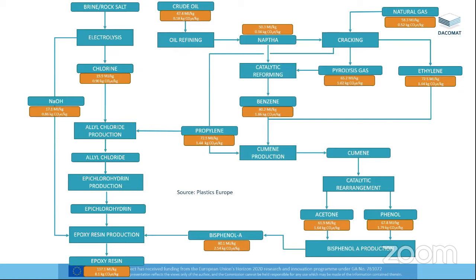What we're basically doing is extracting ingredients, feedstocks from nature, and then we process those feedstocks. So as we pass down a chain to producing, if you look at the bottom left-hand corner, the epoxy resin, which is part of the ingredient of the vinyl ester resin, we have to go through all these intermediates. Now, I've extracted these numbers from the internet, from the Plastics Europe website. And as we pass down, and we're looking at the burdens per kilogram, these will increase. The more processing that you put into making something, obviously the higher will be the embodied energy, and also the higher will be the carbon footprint, which is measured in kilograms carbon dioxide equivalent per kilogram of material.